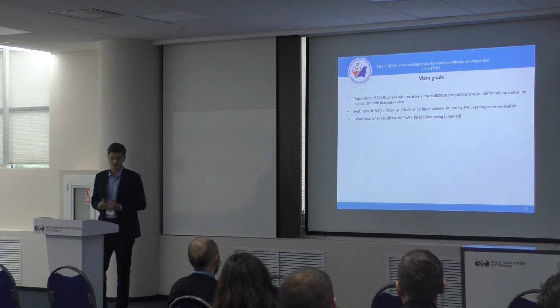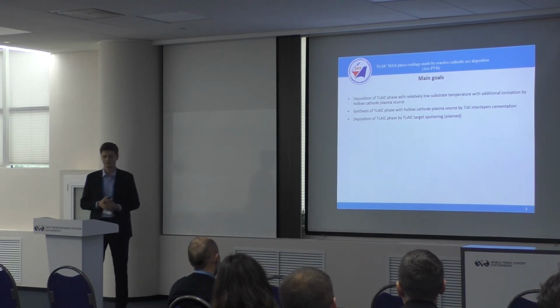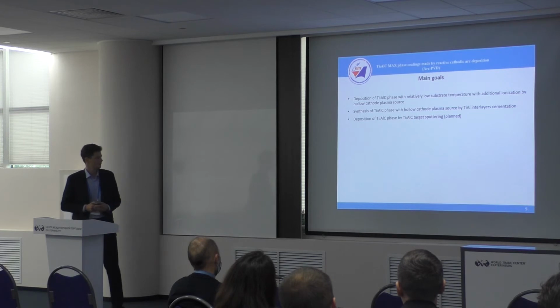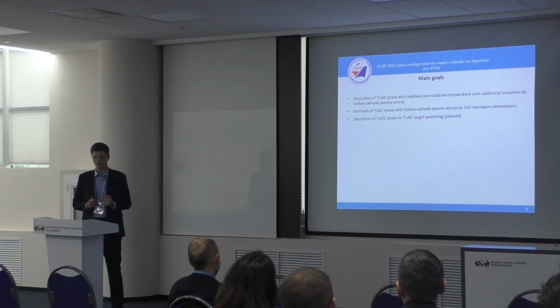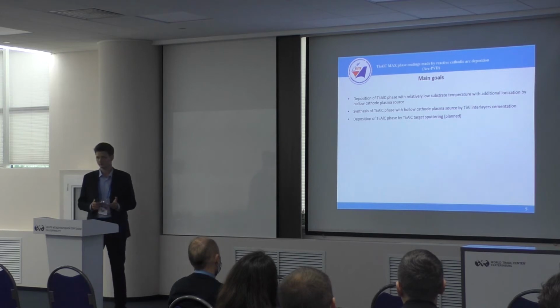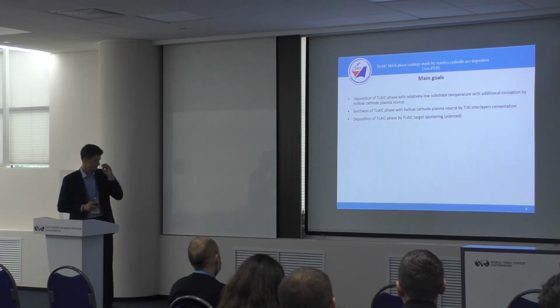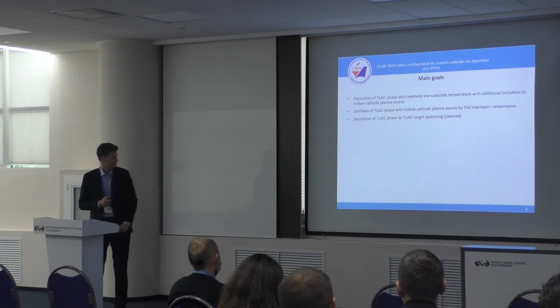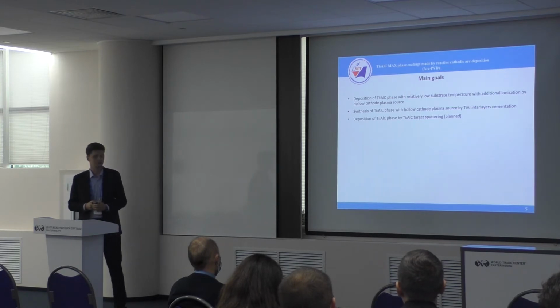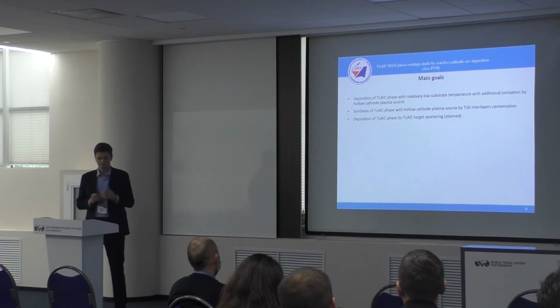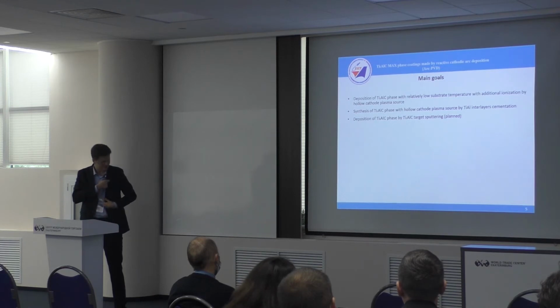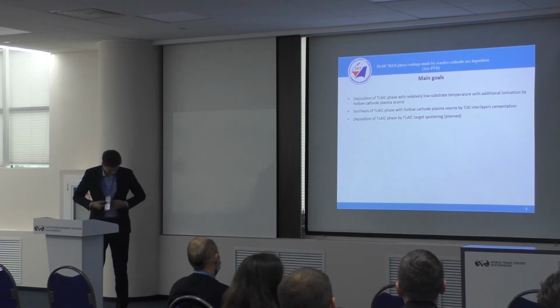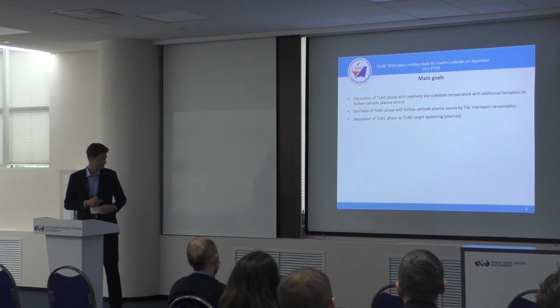The main goals of my work. The first is to try to deposit titanium aluminum carbon MAX phase using two compound targets, titanium and aluminum, without any substrate heating and using the hollow cathode plasma source. The second is synthesis of titanium aluminum carbon MAX phase with the hollow cathode plasma source by titanium aluminum cementation. It's quite low, excuse me. And the third, in the future, is to synthesize MAX phase by MAX phase target sputtering. But we don't have a MAX phase target yet.